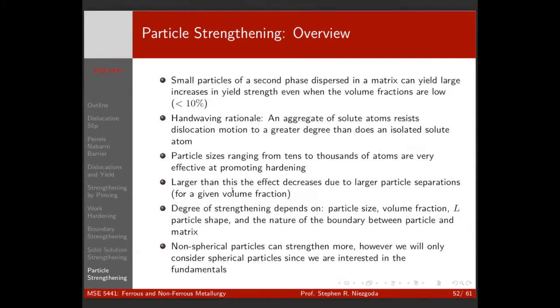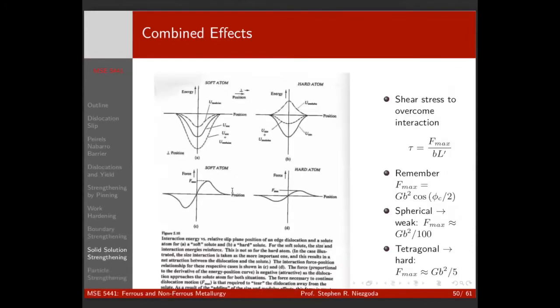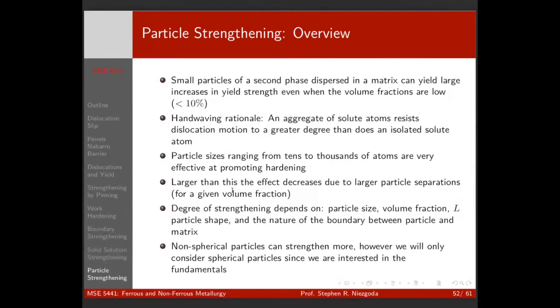So particle strengthening is... just a question. For both the attractive and repulsive, yeah, they both reduce the dislocation movement. Yeah, but attractive reduces more than repulsive. No, it's the simple fact that when you're talking about the size effect, you always have a mix of attractive and repulsive, depending on where it is on the slip plane. So your dislocation will always seek to find a low energy source, right? Whereas with the modulus effect, you're always going to be all positive or all negative, right? And so the lower the energy, it takes more to cut to move away than to be repulsed, right?